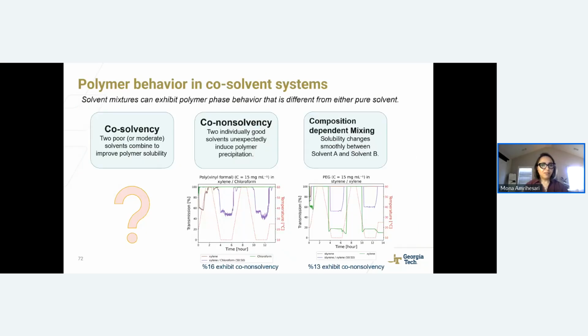We ran 37 experiments, and out of these 37 experiments, we defined some of the conditions that we expected to see. The first is co-solvency, right? When both solvents are below 10%, does that increase the transmissivity to a higher level? Does this 50-50 ratio of the solvents help with co-solvency? Out of the 37 experiments, we have not witnessed any co-solvency happening yet.